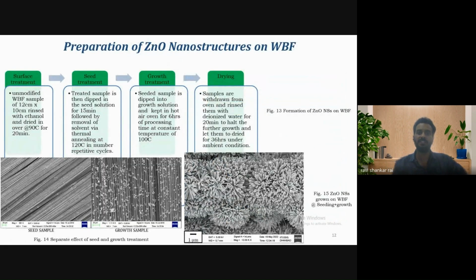So, preparation of the ZnO nanostructure on woven basalt fiber. Initially, we cleaned the sample using ethanol and acetone solution and dried it in an oven at 90 degrees Celsius for 20 minutes. It is just a surface treatment to clean the sample, because during the production or weaving of the fibers, there are some chances of dirt and dust particles sticking.